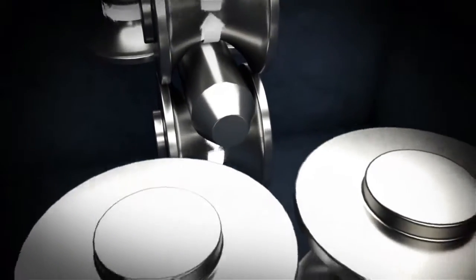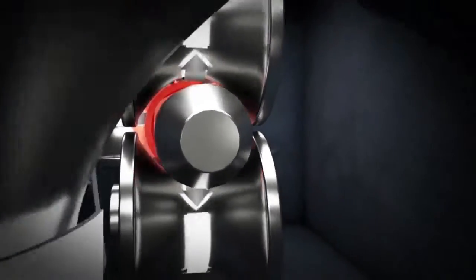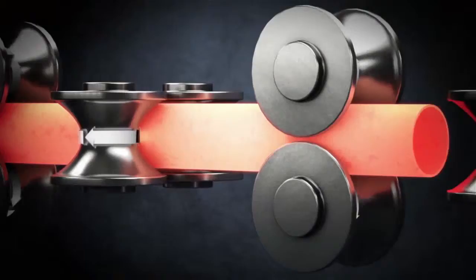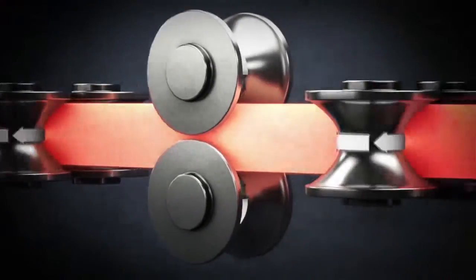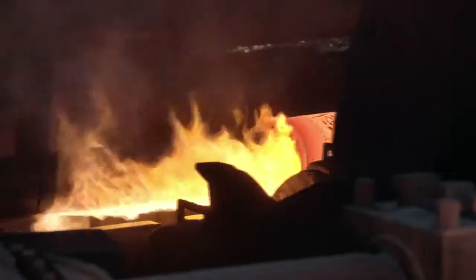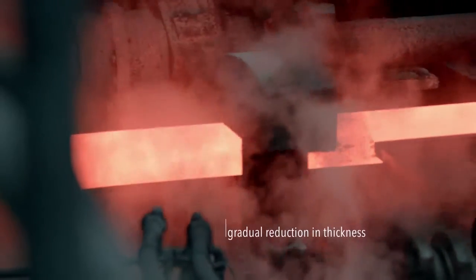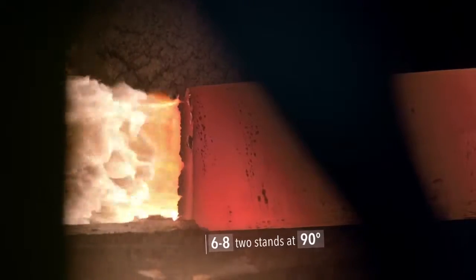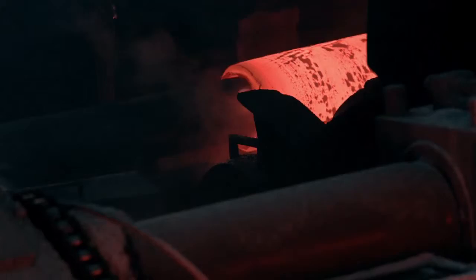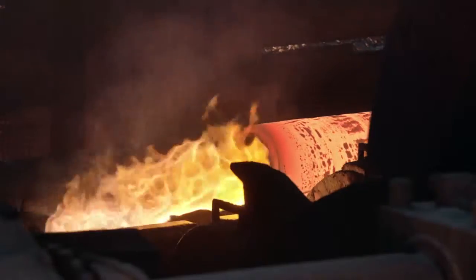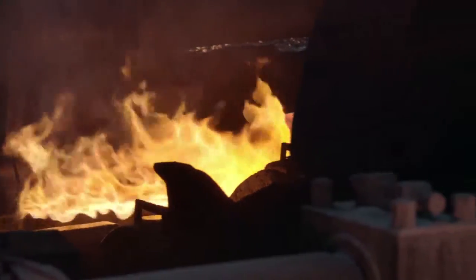Now elongation must occur to turn the shell into a finished hollow tube. Elongation is performed in the mandrel mill by reducing the wall of the hollow shell between 6 to 8 sets of double rollers and a mandrel previously inserted into the hollow shell. During this process, the outside diameter and wall of the hollow shell are reduced,